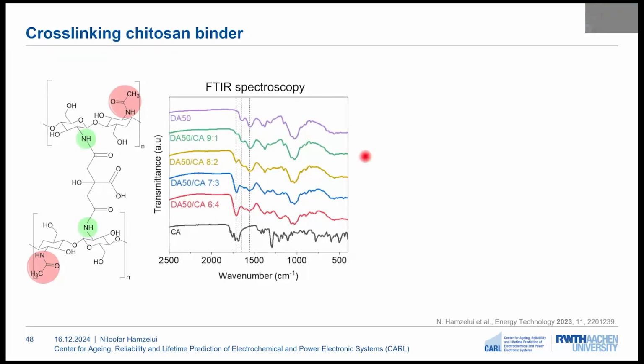The different ratios of DA50 binder to citric acid were investigated, as well as DA50 binder and pure citric acid. FTIR spectroscopy was done, and we can see that at 1721 we have the carboxylic groups in citric acid.